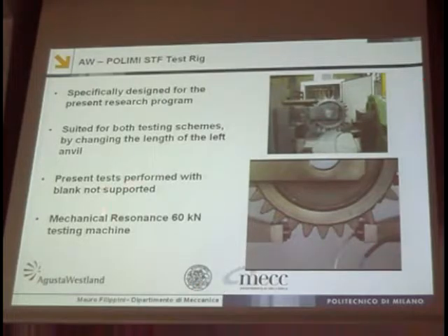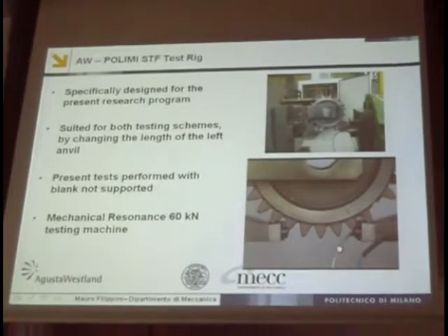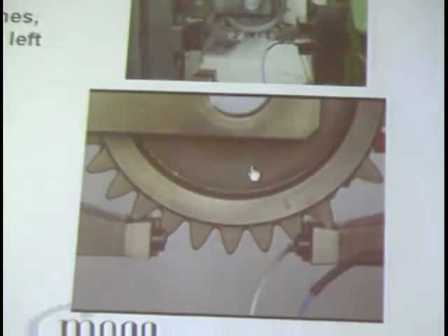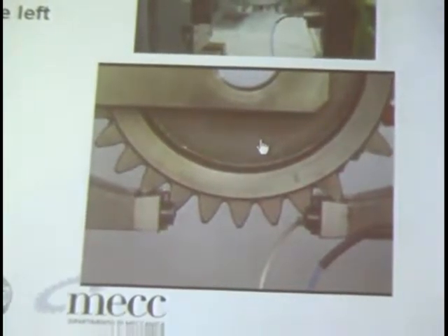So we employ this test rig in which we have this pin that can be removed after positioning the wheel. The modulus is very little, and in this way we ensure that we have a proper positioning of the wheel at the beginning of the fatigue test. And here you will see, you don't hear the noise, but this is the result of the final seconds of the fatigue test. Basically all the life in our test has been spent in initiating a break, and just these few seconds are the last ones, where you see that the wheel is removed from the two anvils.